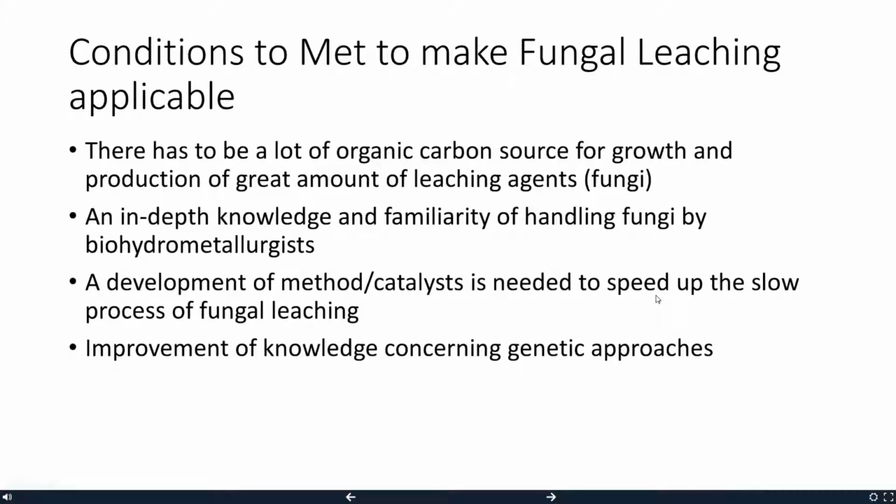But in order to make it applicable, we have to meet these conditions. First, there has to be a lot of organic carbon sources, as fungal leaching needs a lot of carbon source to grow. And then for a second requirement, it needs in-depth knowledge and familiarity of handling fungi by hydrometallurgists, and also development of a method of catalyst is needed to speed up the slow process of fungal leaching, because it is very slow compared to other methods. And also the improvement of knowledge concerning genetic approaches is necessary.